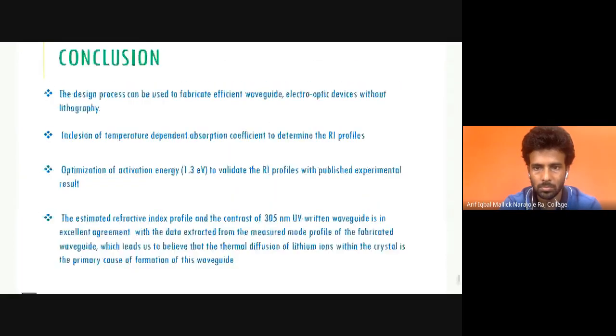Finally, we discuss the conclusion. The design process can be used to fabricate efficient waveguide electro-optic devices without lithography. We included a temperature dependent absorption coefficient to determine the refractive index profile, and optimized the activation energy to validate it. The estimated refractive index profile of 305 nanometer UV written waveguides is in excellent agreement with the measured mode profile. The waveguide fabrication is attributed to the thermal diffusion of lithium ions. That's all. Thank you.